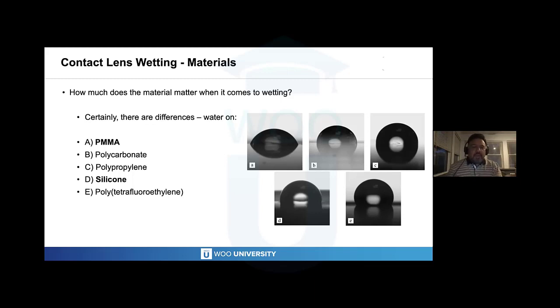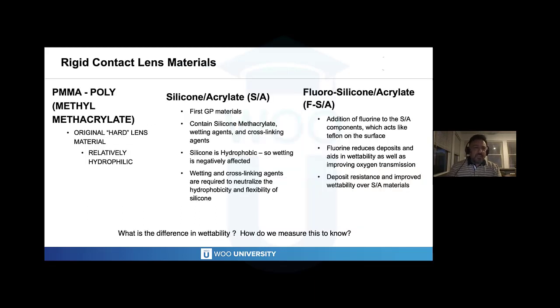So we're fighting that battle of oxygen permeability impacting the lens's surface wetting. Again, as we look at rigid contact lens materials over the years, we started with our PMMA material, and then we moved, of course, to the silicone infused materials, which helped with oxygen permeability, which is very critical, because obviously we know with PMMA is the impact on the health of the cornea long term.